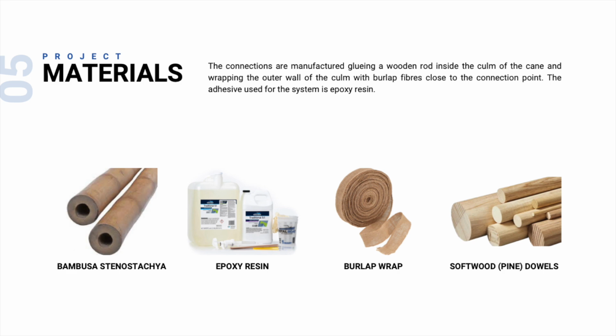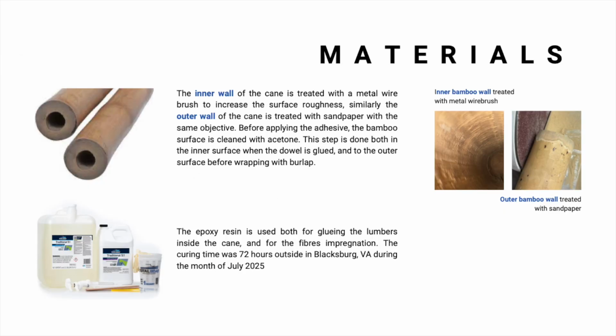So I used wooden dowels, like I said before, glued into the bamboo canes with epoxy resin. Around the outside of the joint, I added a wrap of burlap fibers, also impregnated with epoxy. To improve the bonding, the surface preparation was really important. So the inner wall of the bamboo was brushed with a metal wire brush, and then the outer wall was sanded with sandpaper, and both were cleaned with acetone to remove dust and impurities.